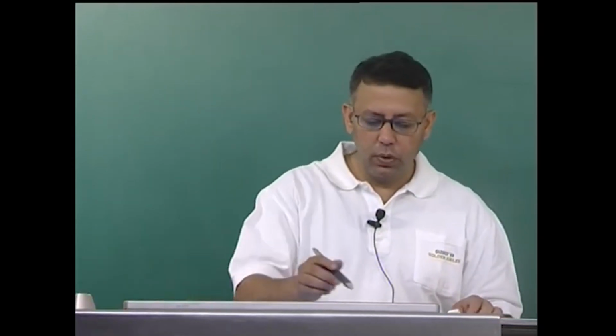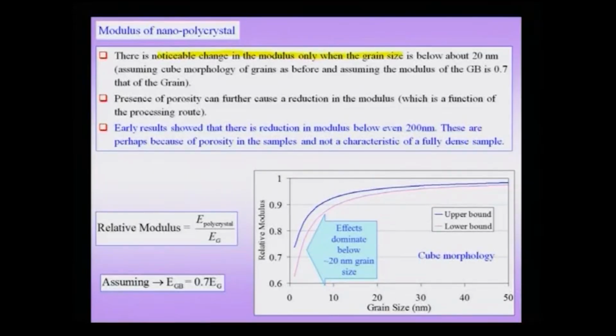Now, we are told that a nano polycrystal can be thought of as a composite of grains and grain boundaries and triple lines and other kinds of defects. For a first order, we can think of a nano polycrystal as a composite of the grains and these other defected regions in the polycrystal, which we saw just now, that have a lower density as compared to the bulk of the grain. These regions are also expected to have a lower modulus, because the bonding is inferior as compared to the bulk of the crystal. Now, we notice that there is a bulk change in modulus only when the grain size is below about 20 nanometers.